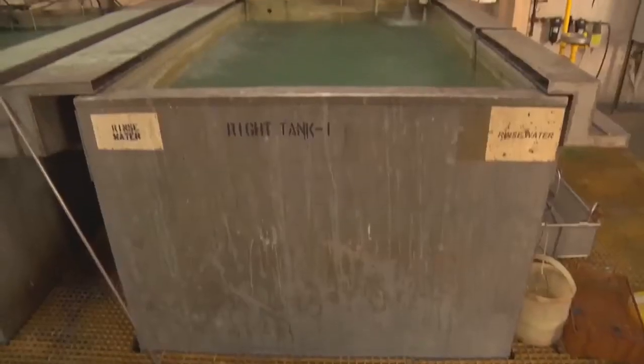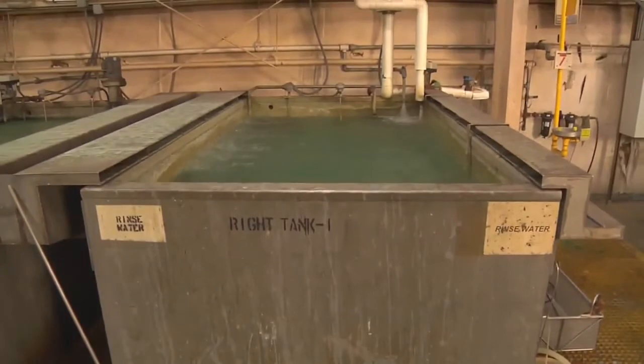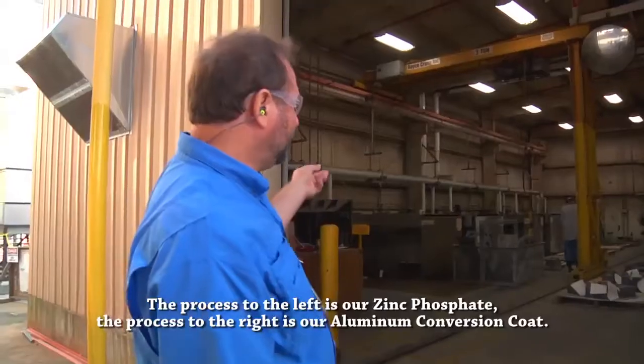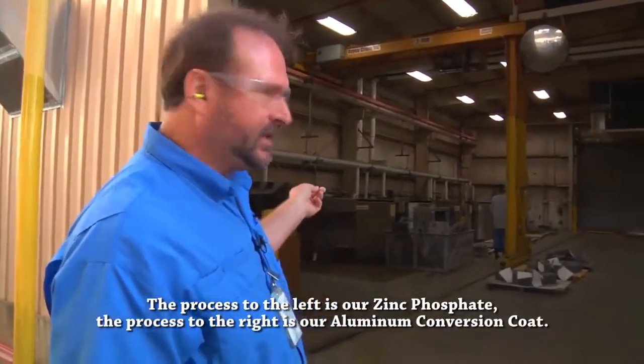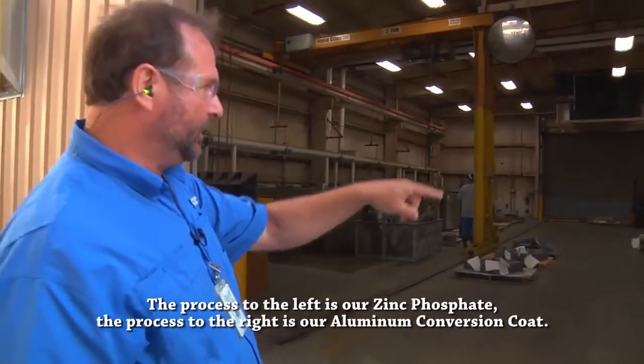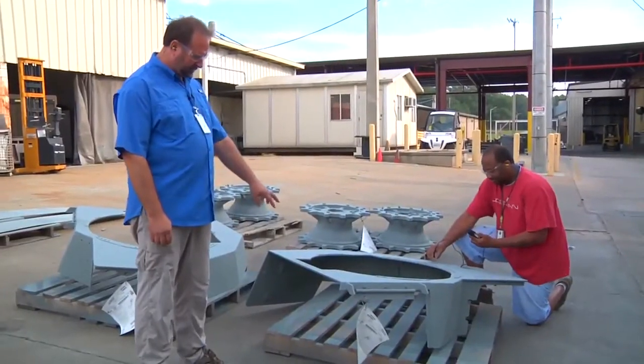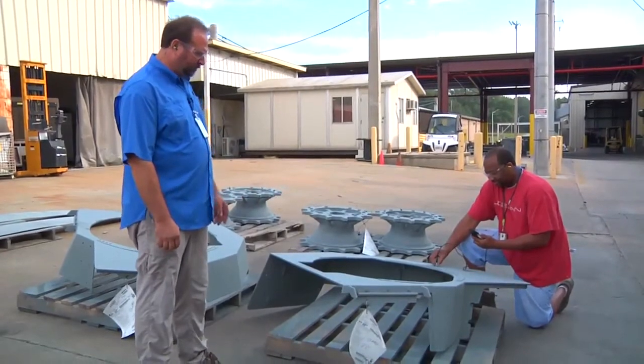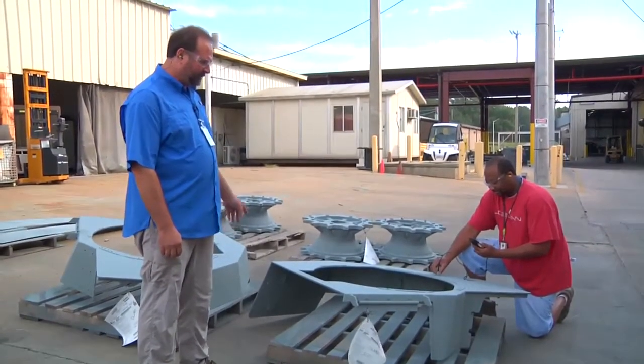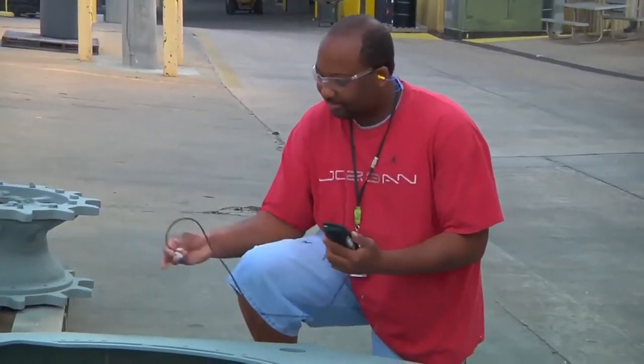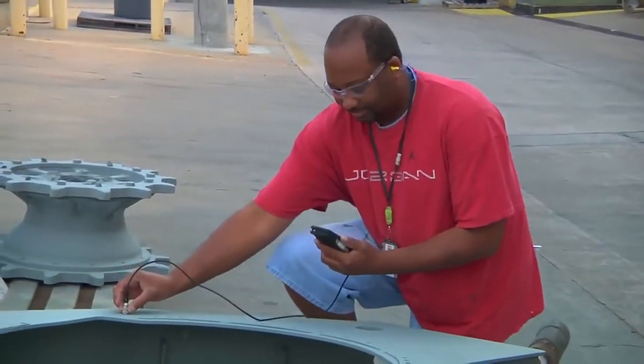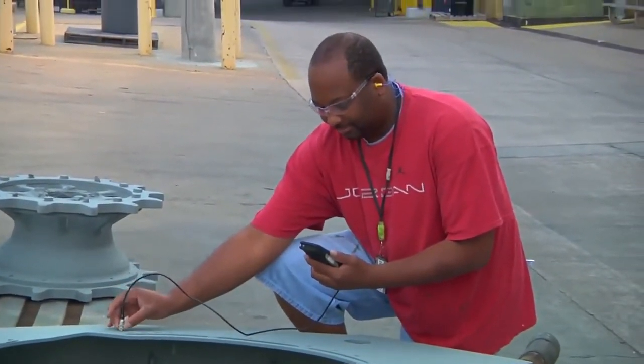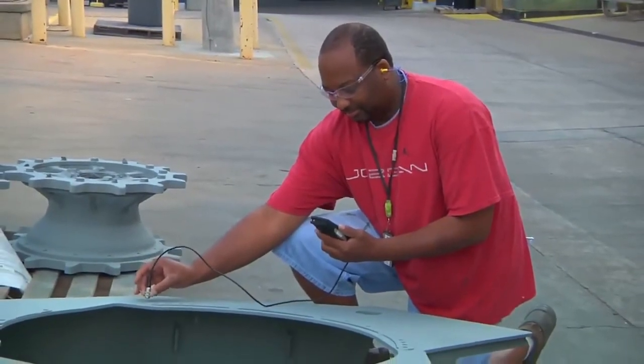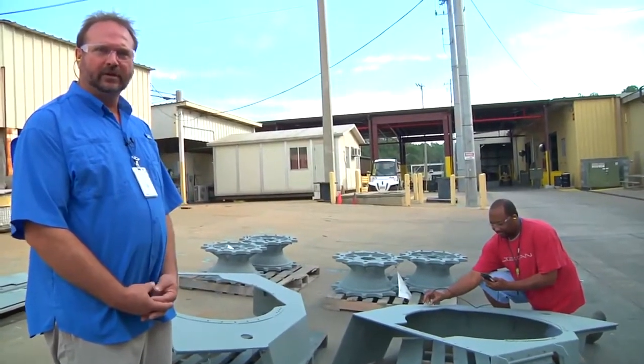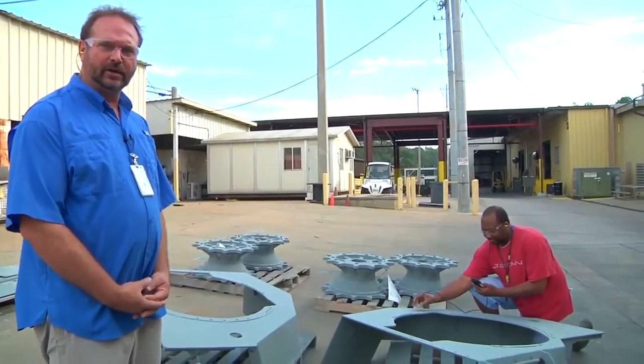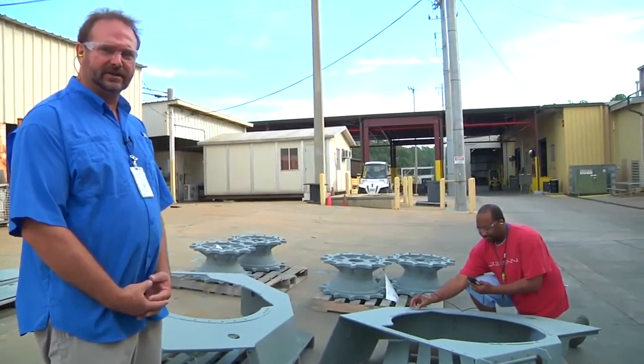So this is our immersion tank, zinc phosphate, aluminum conversion coat area. You can see the process to the left is our zinc phosphate, the process to the right is our aluminum conversion coat. This item is a steel item that's had zinc applied, and what he's doing now is taking an average of the coating thickness to make sure that we have it properly applied and in the proper amount. What we do in the component area as far as the QA process is 5 components per shift will be randomly selected to make sure each step of the process is as it's supposed to be.